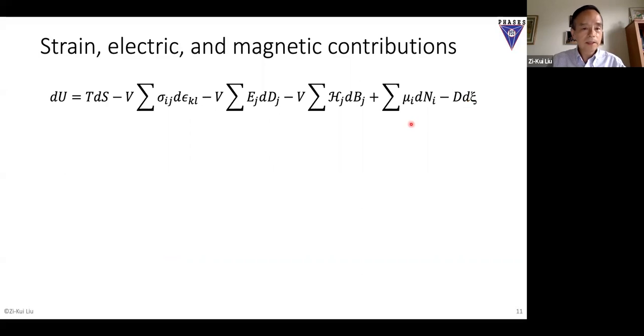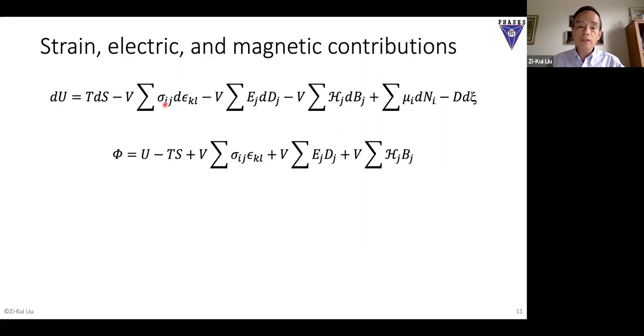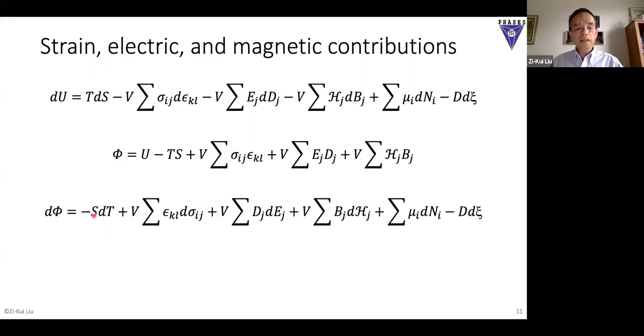And this is driving force. But most of the time, we do not control the electric displacement. We control the electric field or magnetic field, right? Or you control the stress. So then you do a conversion. That's the Legendre transformation, like we did for Gibbs energy. You can transform all of them, define another free energy phi. They can do d phi. So d phi now is minus SdT, and now all of these change sign. You get the stress, electric field, and magnetic field. But we keep this one because we usually control the mass of the system. Then you have driving force for internal process. So this is, of course, most useful to us because the natural variables of phi are what we control in experiments. So now you can see the phi for all of this uniform differential.